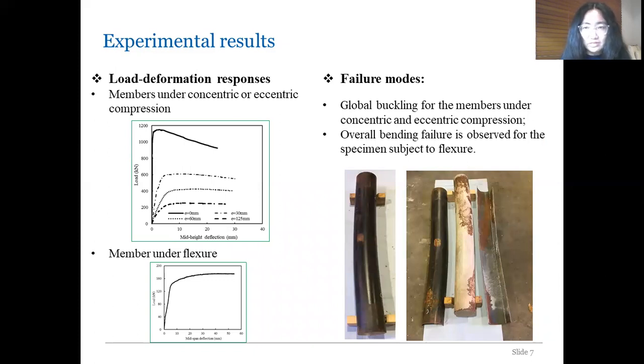And to investigate the geopolymer concrete core within the steel tube, I cut one specimen open after testing, as shown in the figure near the bottom on the right-hand side. As you can see from the photo, the geopolymer concrete maintained its integrity without the severe spalling observed by other researchers when the structure was reinforced inside by bars. On the tensile side, I observed some minor transverse tensile cracks. So it shows that the steel tube provides quite effective confinement to the geopolymer concrete.